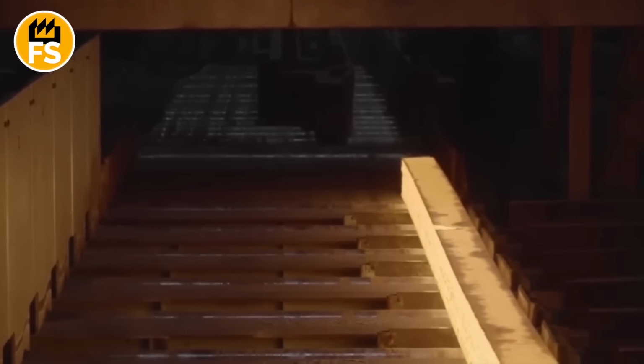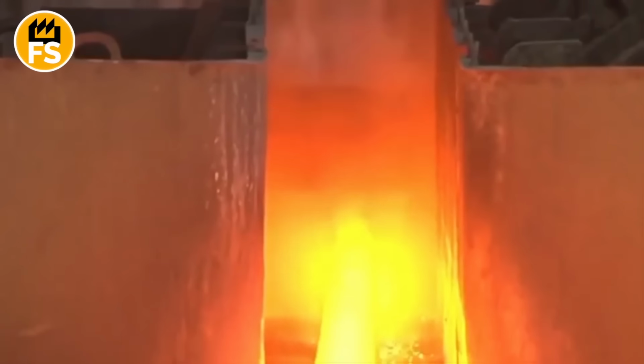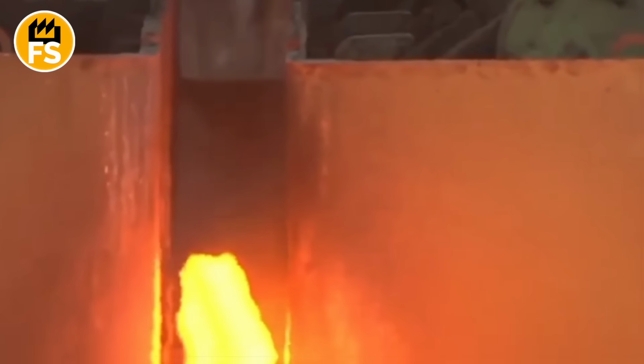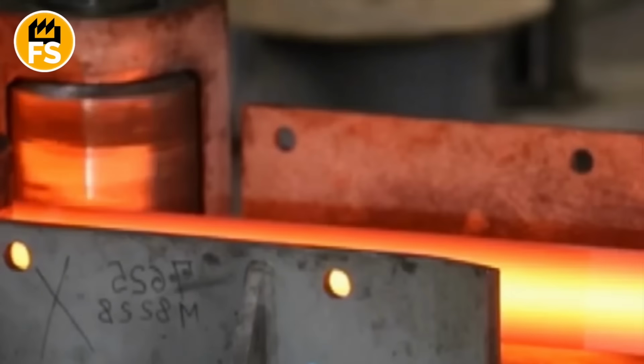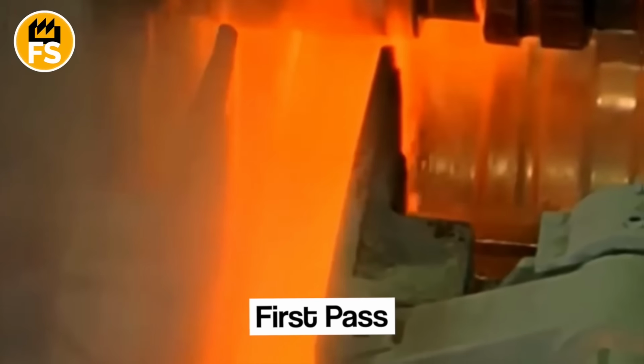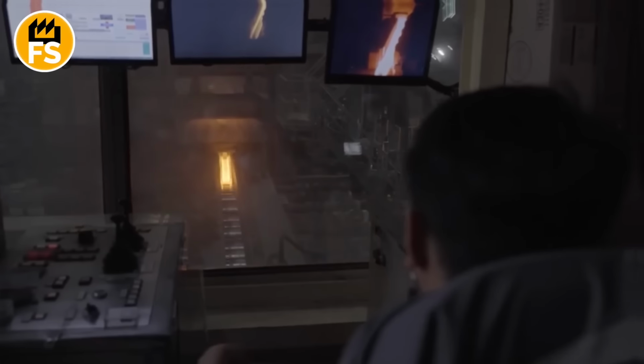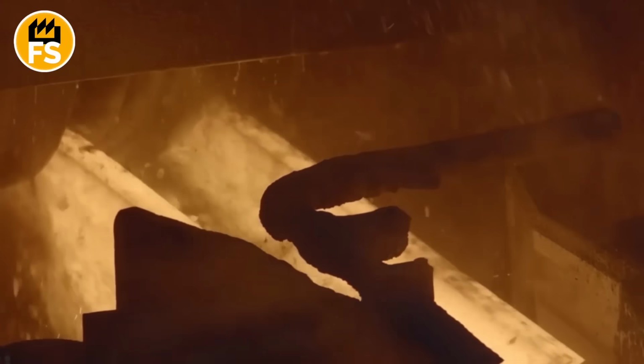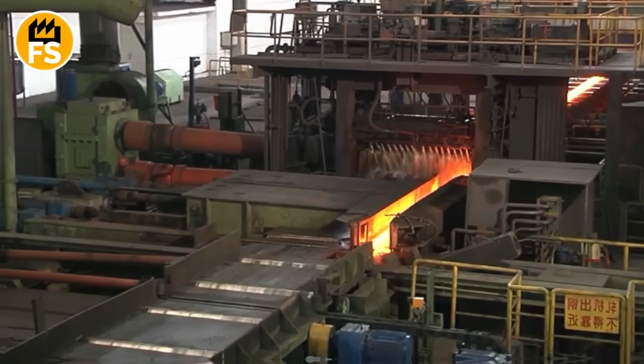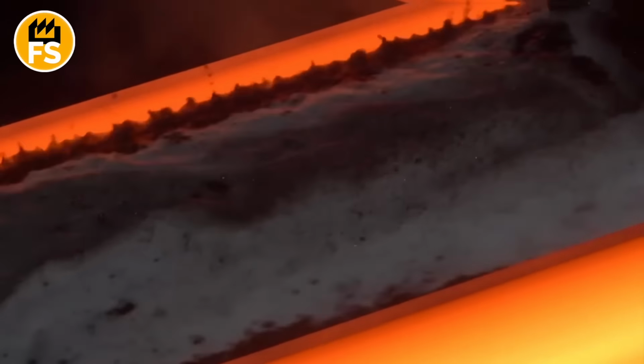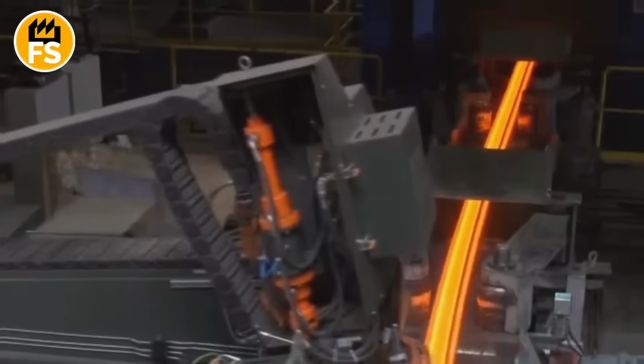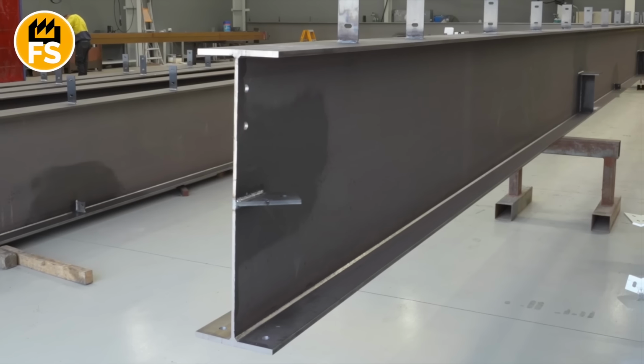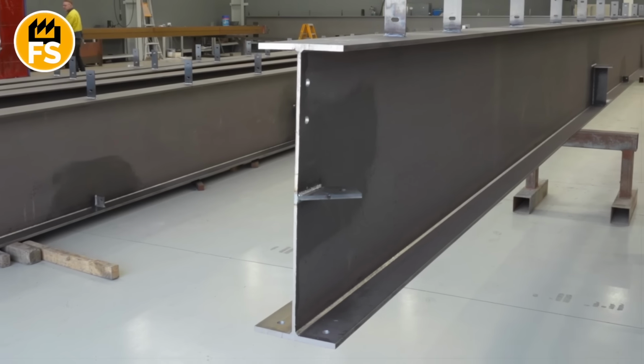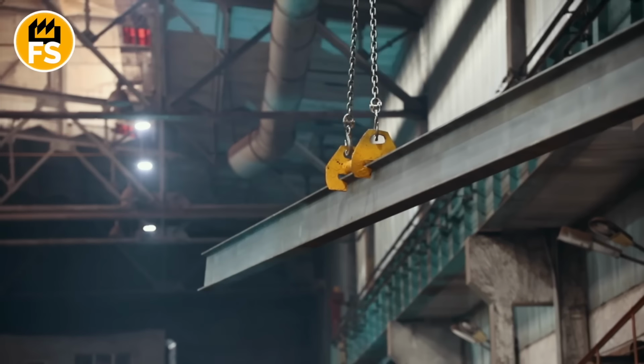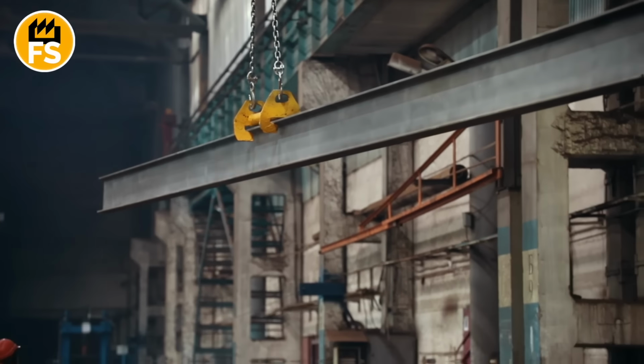The glowing steel passes through a series of massive rollers, and each set of rollers has a different shape cut into it that progressively forms the W profile. In the first pass, the bloom gets compressed and starts elongating, and you can literally see the metal flowing like thick honey as these rollers that are applying thousands of tons of pressure reshape it. After about 12 passes through different roller sets, the distinctive W shape starts emerging. You've got the wide horizontal flanges on the top and bottom that provide strength against bending, and the vertical web in the middle that provides stability against twisting.